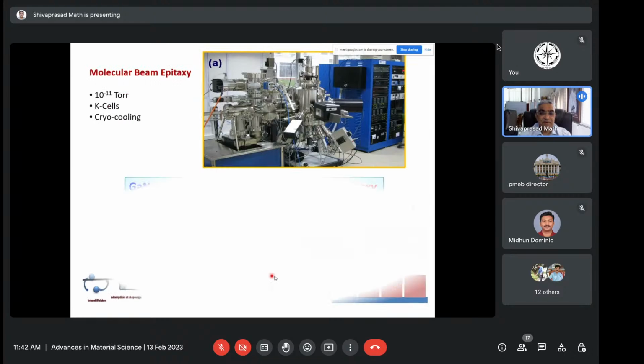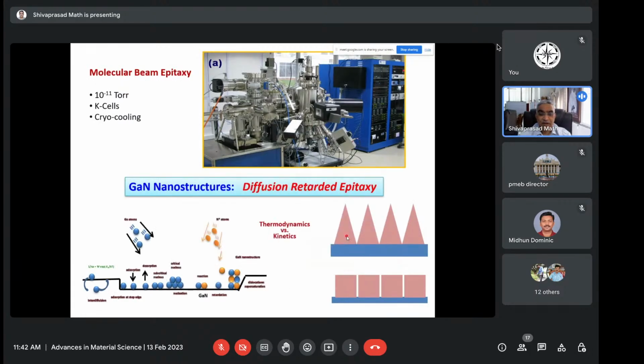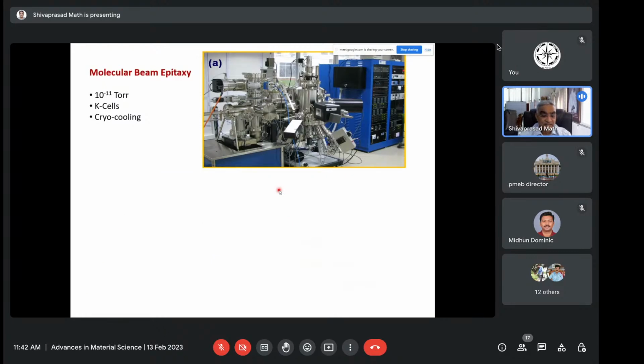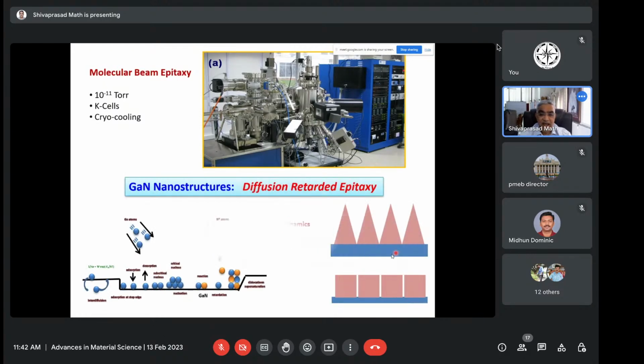Then in an MBE chamber, we wanted to grow material. One of the problems with gallium nitride is that it doesn't have a native substrate, which means I have to grow it on some other substrate. Sapphire is a beautiful substrate. Now, of course, we are also working on silicon and other substrates. Even silicon carbide is a beautiful substrate, but very expensive and also not transparent. So we need a substrate which is transparent as well as matches the lattice parameter, and that does not happen very well.